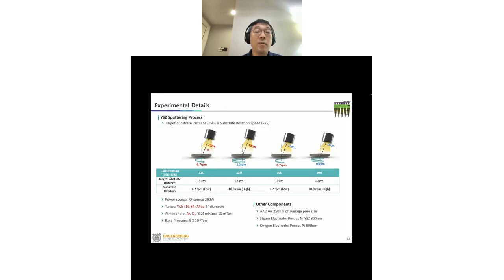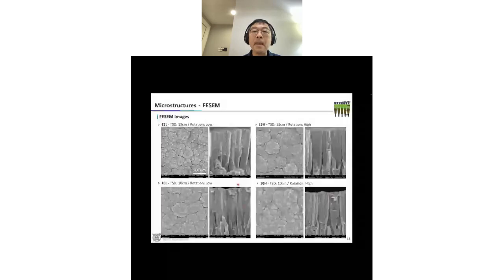So to achieve that, we use oxygen, an oxygen plasma environment. These metal targets are turned into plasma, and then they oxidize, and then they deposit onto the cell surface and form the YSZ, the oxide ceramic membrane. Okay, so here are some observations first.